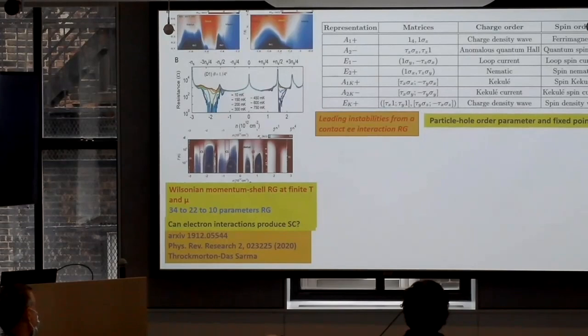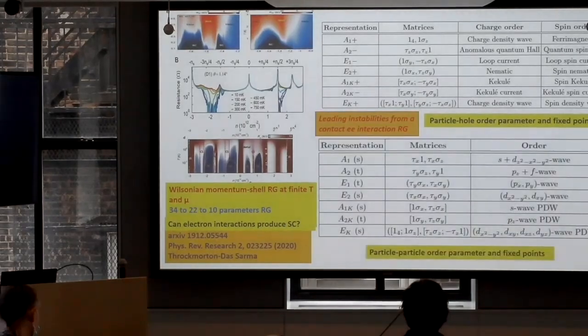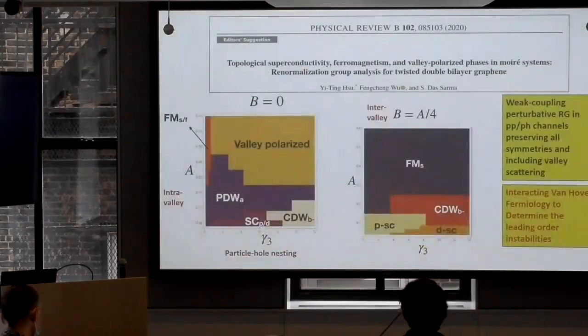It's a contact electron interaction, but we found lots and lots of fragile states, which I think is consistent with the experiment. No two samples show exactly the same phase diagram. There are many, many phases, and all of those phases are coming from electron-electron interaction, okay? And the superconductivity is invariably some high orbital superconductivity, which is what we expect. I'm not going to talk about this. This is just to say that it's not like we ignored electron-electron interaction completely. We did the calculation that everybody else does, in our own language, and we found topological superconductivity. We found all kinds of density waves and the superconductivity P and D.